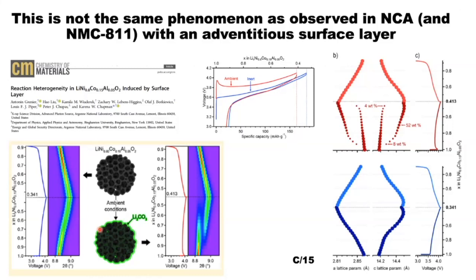I just want to make one point before I move on and show you this analysis, and that is to say that what he's seeing is very distinct from the two phases that you see if you take, for example, an NCA or an NMC-811 and you leave them in the air and they build up a lithium carbonate or hydroxycarbonate coating.